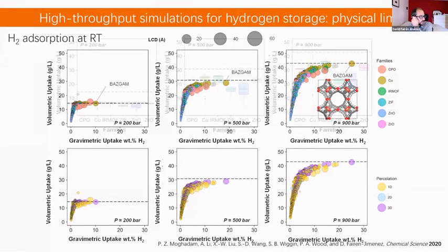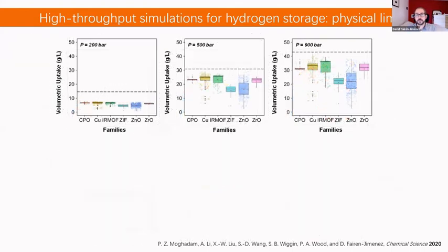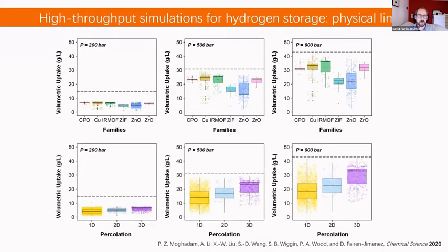And we can also apply big data tools, not only for data visualization. So we can start studying the different statistics for all these different materials. At 200 bar, we can see how spread the results are. And if we work at extremely high pressures of 900 bar, for example, you can see for this family of materials very low capacity or much higher capacity, whereas these zirconium MOFs, in general, perform much better than all these ones. So this is something that we can always study and evaluate.